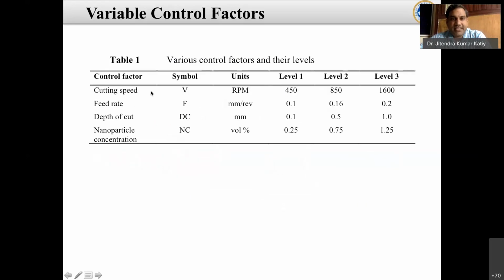These are the various factors which I consider at three levels: 450, 850, and 1600 RPM, feed rate, and depth of cut from 0.1 to 0.2, and nanoparticle concentration. So 0.25 means 0.125 concentration of graphite and 0.125 concentration of talc. Why did I choose graphite and talc? Because graphite gives a low coefficient of friction and talc gives high wear resistance. I have also published many papers on graphite and talc during my doctorate, so I thought I could choose them here and observe that factor in the output parameters.